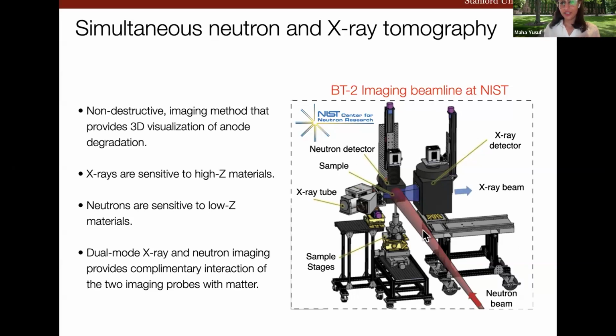You can see in this schematic, we have a neutron beam, which is produced by a neutron reactor, and we have a microfocus laboratory-based X-ray source, which is producing an X-ray beam. Now, the neutron and X-ray beams here are roughly perpendicular to each other, and they hit the sample at the same time during the imaging experiment. And then we have a neutron detector and an X-ray detector that detect the neutrons and X-rays after they have interacted with the sample, providing us a neutron and an X-ray image. Then I take the data from both of these neutron and X-ray images to do dual mode segmentation.